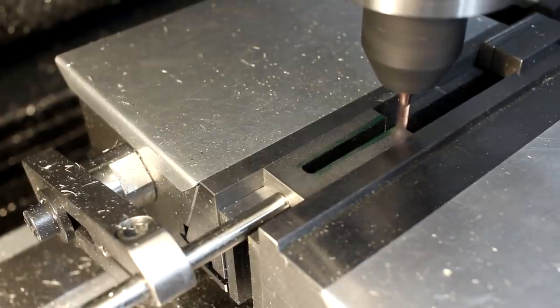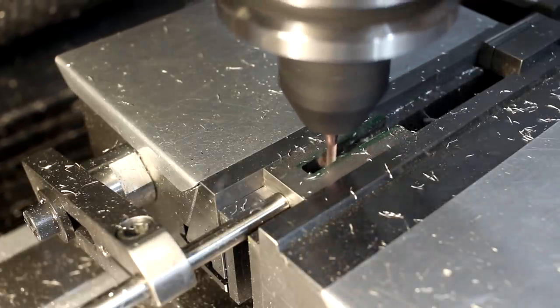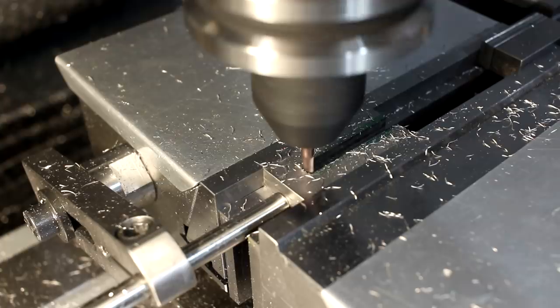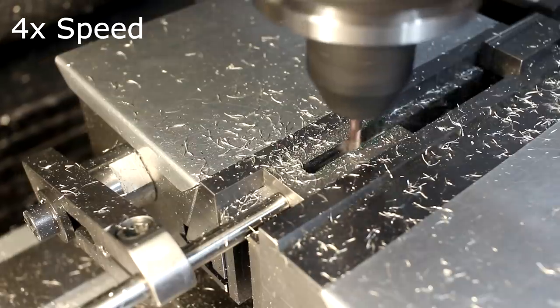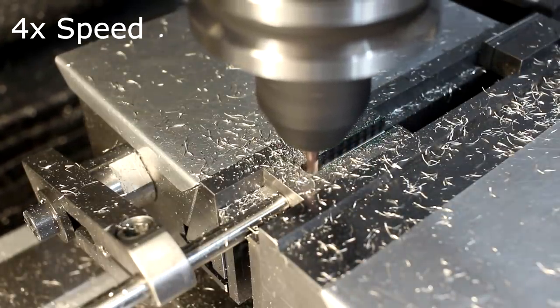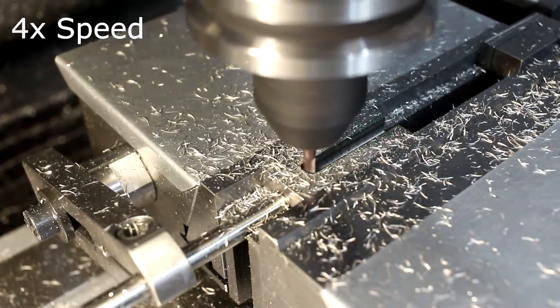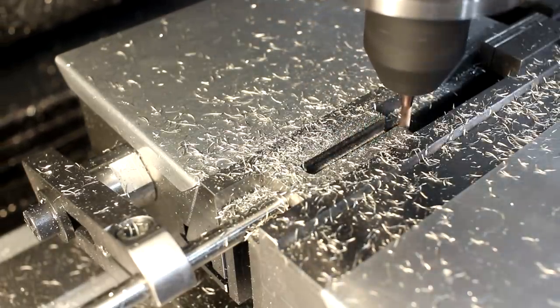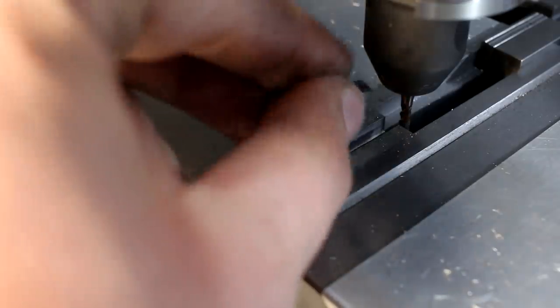High speed steel cutters tend to get deflected more because high speed steel is three times less stiff than carbide. So a spring pass will always be necessary. There we go. That's a four millimeter gauge block. Looking good to me. Now we cut the step at full depth to size. Roughing in two side steps and then finishing.